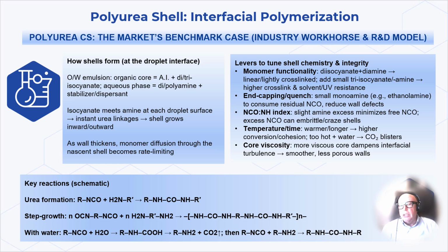Monomer functionality: linear gives fast release, trifunctional gives stronger shells but slower release. Temperature and time: higher gives better conversion. NCO to NH ratio: slight amine excess prevents brittle shells.